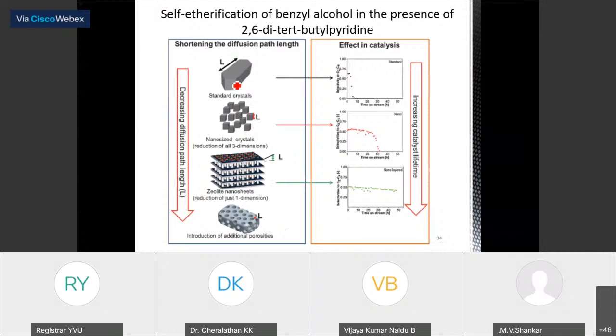So the people have studied different hierarchical zeolites, nanozeolites, and pillared nanosheets, macroporous zeolite, and all this. So you can see when you have this kind of hierarchical pores or nano-size zeolites, the stability of the catalyst, the lifetime of the catalyst can be increased. Okay, this is conventional microporous. This is time on stream, and the lifetime is small. But if you have this kind of pillared layers, your lifetime is enhanced enormously. It is mainly due to this introduction of the hierarchical porosity and reduction of the diffusion path.